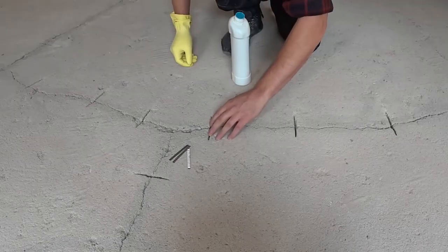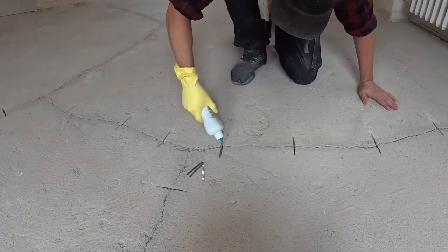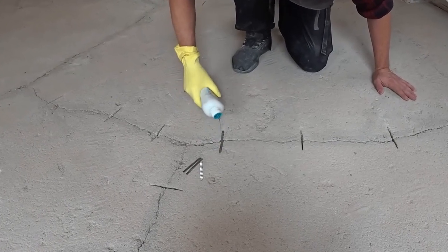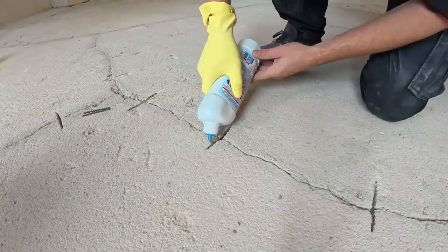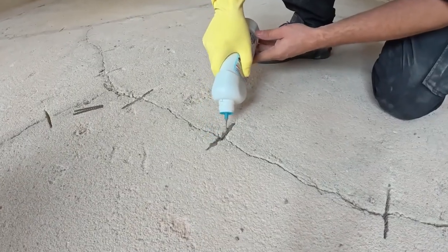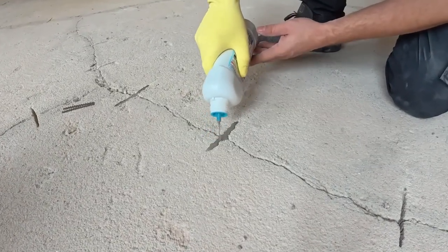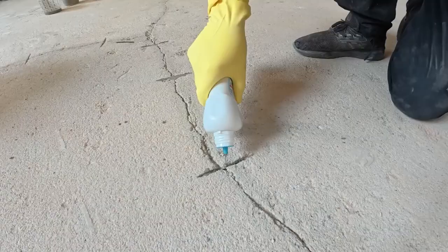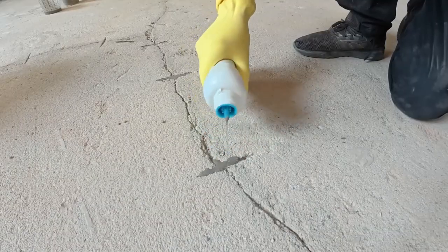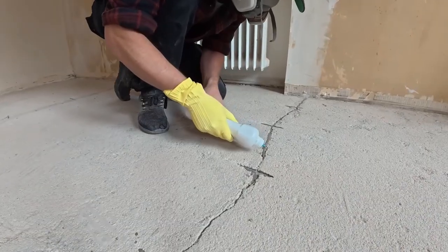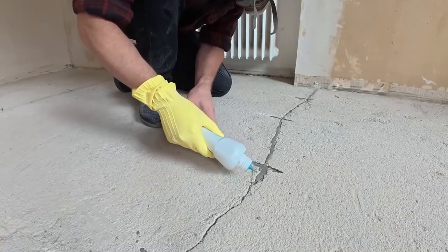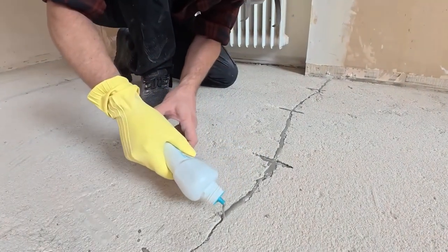When filling the cracks, you have to be careful not to pour in too much resin. What I did here was work in 2 steps. That proved to be effective. In the first pass, I filled the crack with resin up to the top edge. Then I waited a short while, and the resin settles down a bit in the crack, is partly absorbed by the concrete, and then in the second pass you can fill the crack completely up to the top edge with resin again.